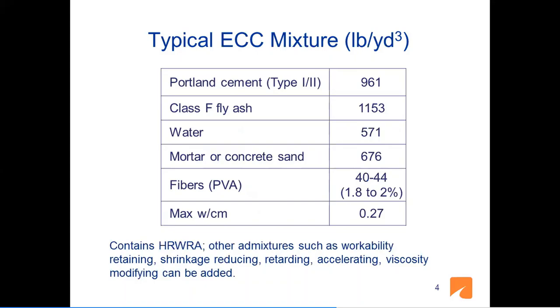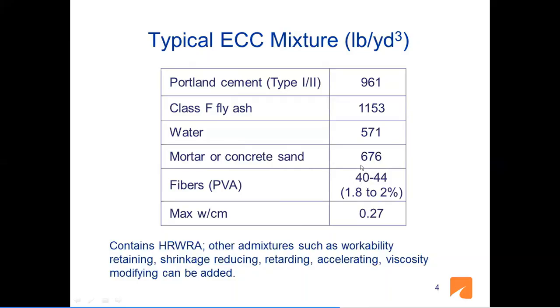And then we use fibers. When Dr. Li developed this, he used 2% fibers by volume, which is about 44 pounds per cubic yard. But when you buy fibers, they come in 40-pound bags, so it turns out to be 1.8%. That's why I put both of these numbers here, 1.8% to 2%. So a bag of PVA fiber is 40 pounds. And the maximum water-cementitious ratio is 0.27, so it's a pretty low water-cement ratio.